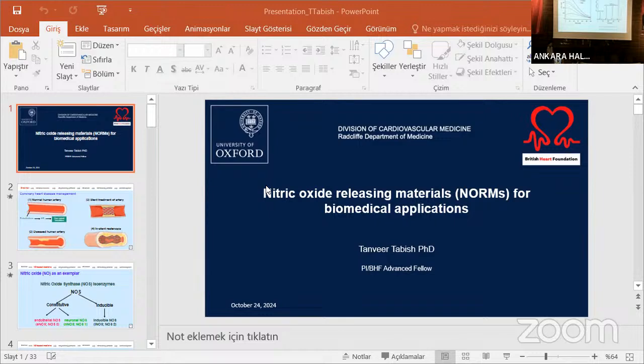So this was using an electrochemical sensor to show the real-time production of nitric oxide, and the next one is a chemiluminescence nitric oxide analyzer to show how much in total we can produce. So you can see out of 10 micromolar GSNO, we can produce around 6 micromolar. That's quite high. But if we just use the nitric oxide source, we can only produce up to 2 micromolar. That's not really useful. So we use this on stent materials to show that graphene can be successfully conjugated